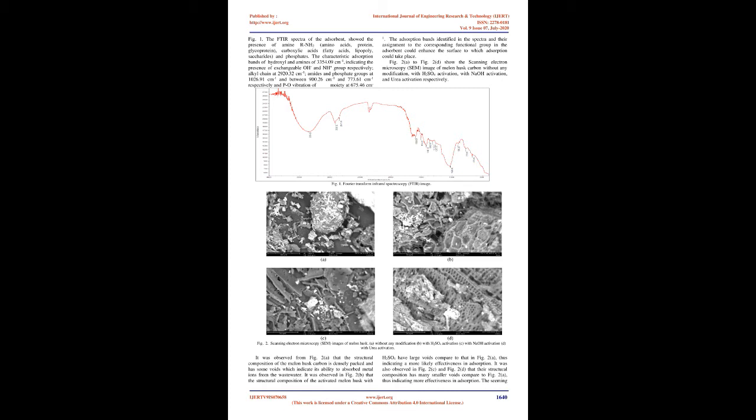Melon husk activated by urea. Nwankwo and Mogbo, 2014, activation method was used. 100 g of carbonized melon husks was soaked in 0.6 g/cm³ urea solution for 6 hours, drained and dried overnight at 50°C and was further activated at 120°C for 4 hours using a memmert oven. The urea-activated melon husk carbon was stored in an airtight container ready for use.